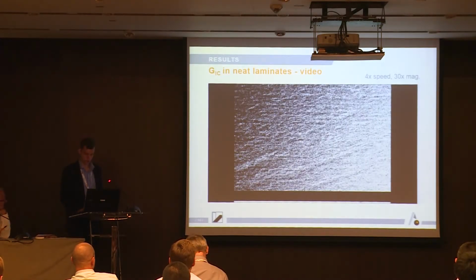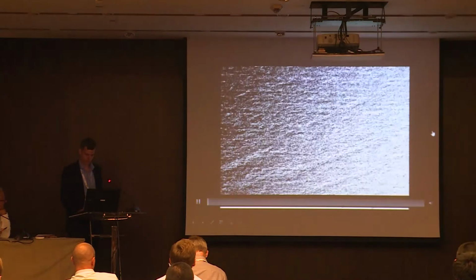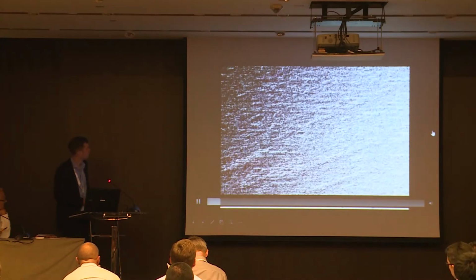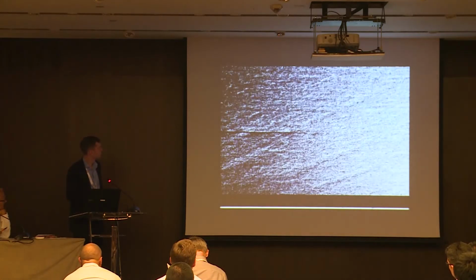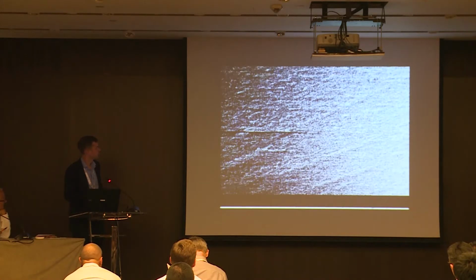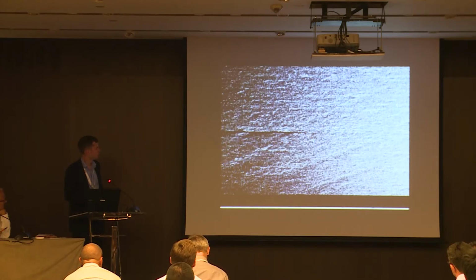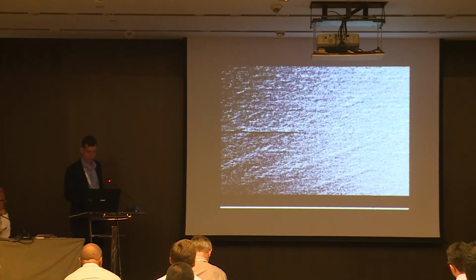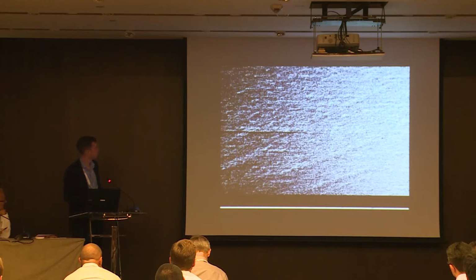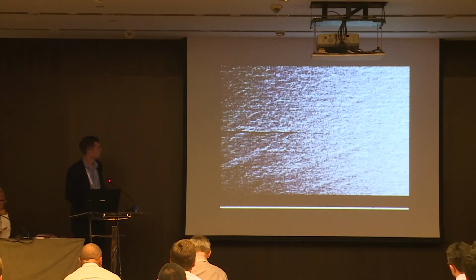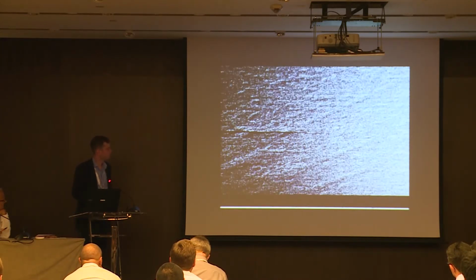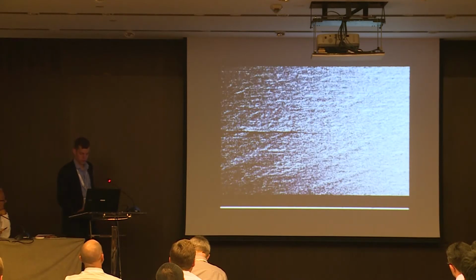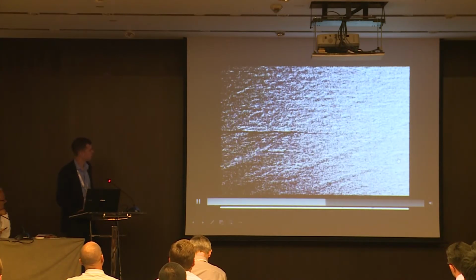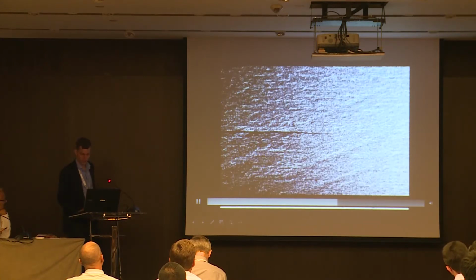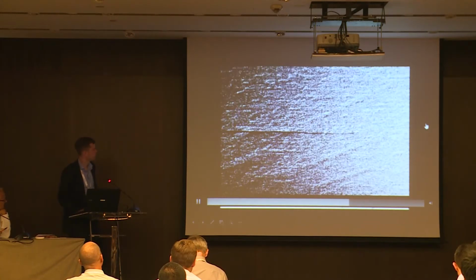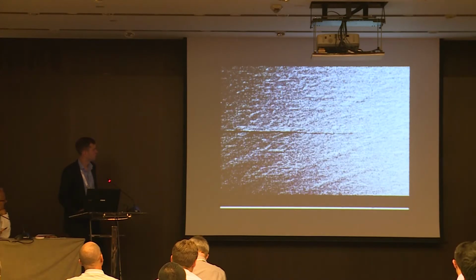Now you can generate these videos from SEM. You can see again that the crack moves from the left side to the right side. I sped up this video by roughly 4 times so we can see something. This crack then slowly grows. I guess one can improve the quality of this picture by running it slower, but to have a comparison to the quasi-static test, I ran it at the same speed.